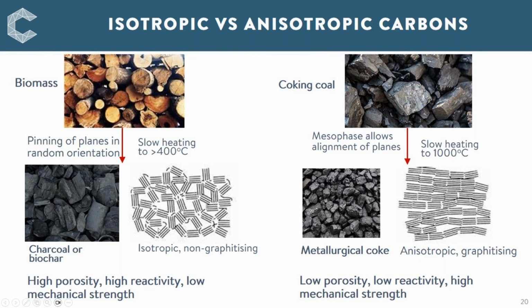Now, charcoal has the carbon structure that's depicted to the right of that image of charcoal. Each of those little stacked layers represents a kind of graphite-like crystallite, a small region, nanometers in size, of aligned planes that look a bit like graphite. But all these crystallites are randomly oriented, and they're in an amorphous carbon structure as well. So this is known as isotropic carbon. And isotropic carbons, because of this random orientation of the crystallites, create a very porous, microporous structure. It's great for activated carbons, high surface area. But this also means that charcoals have inherently high reactivity compared to coke, which I'll talk about in a moment, and low mechanical strength because of their structure.